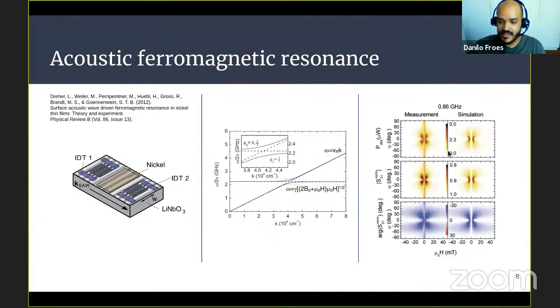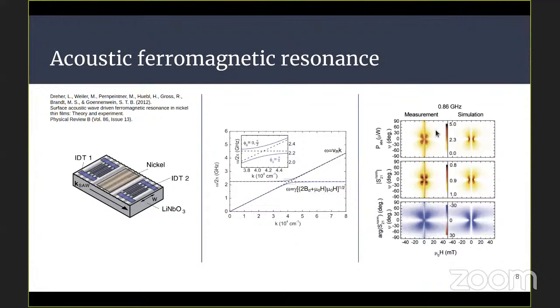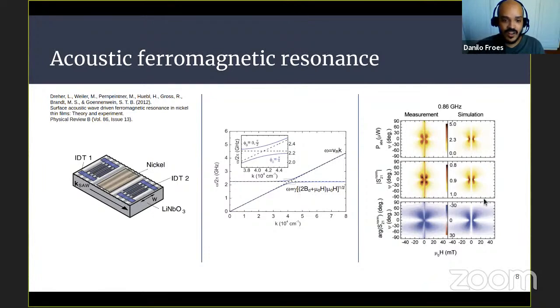And here on the right, another characteristic is that the coupling between the spin waves and the elastic waves is optimized when the angle between the K, the wave direction, and the magnetization is not perpendicular or parallel. It's maximized when it has an angle. So 45 degrees, for instance, for some setups is the maximum. So we have this angle variation and we have this splitting of the curves due to the hybridization.